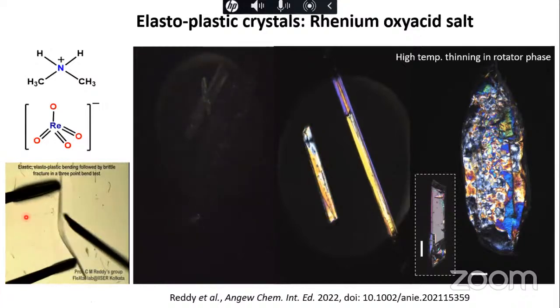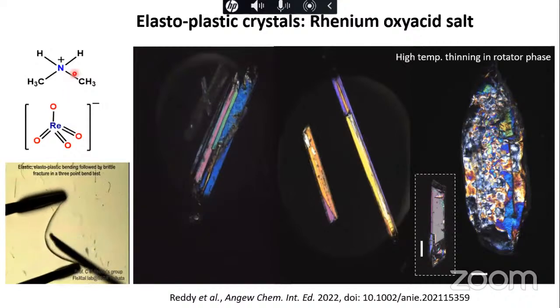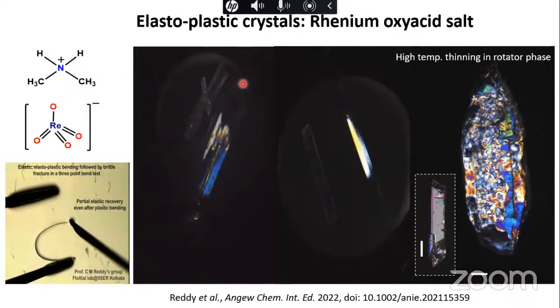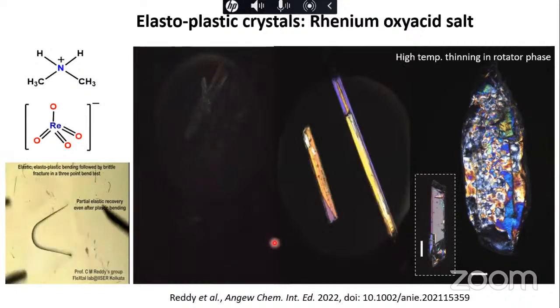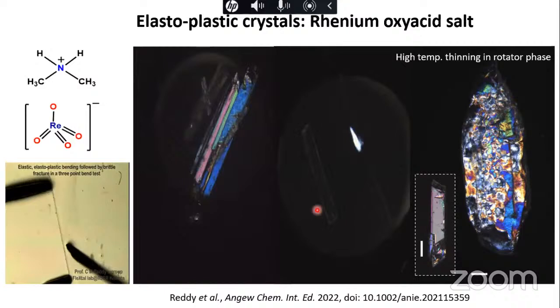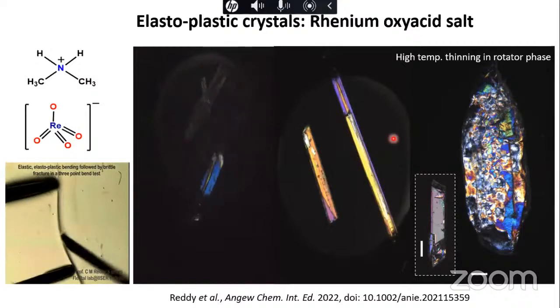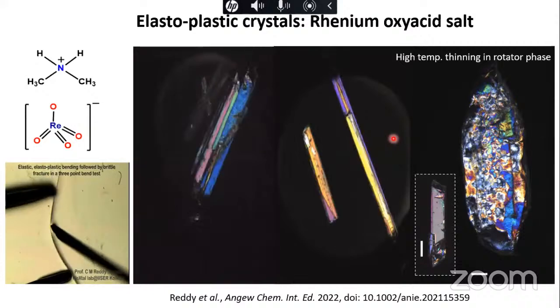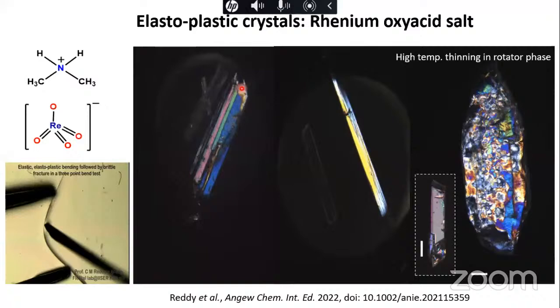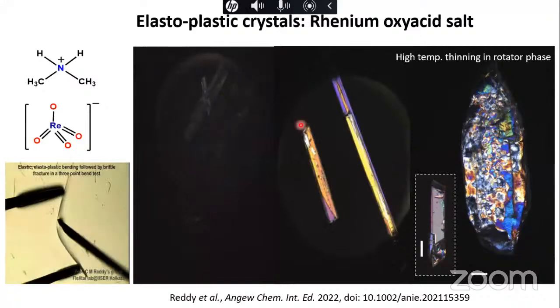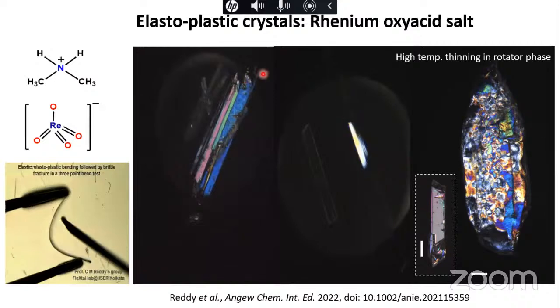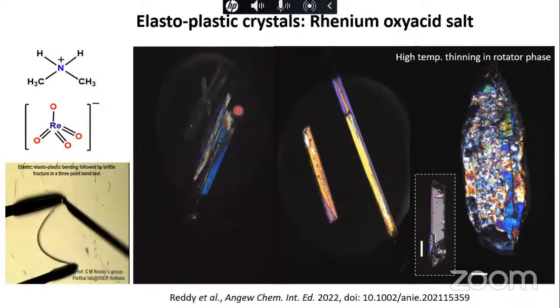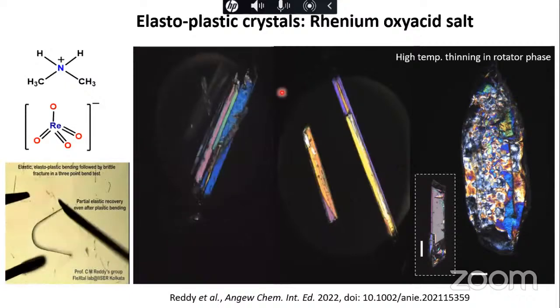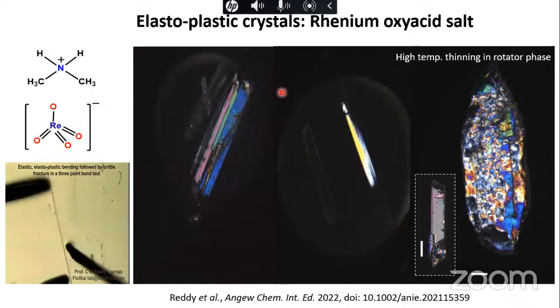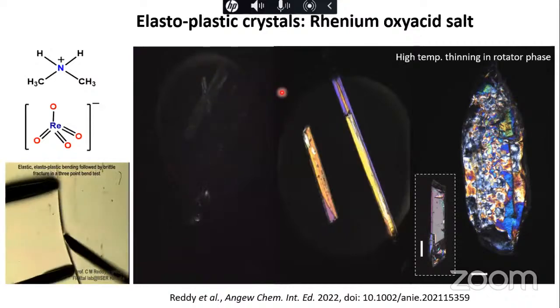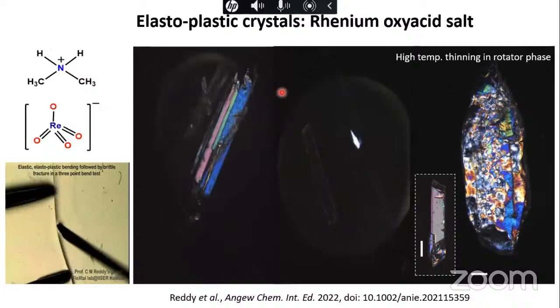At room temperature, these are like normal static crystals. But when you heat them beyond a certain temperature, as you can see, the crystals go into the plastically disordered phase. That means the molecules start rotating after a point, and it goes into the rotator or plastic crystalline phase. Once it does, it loses this iridescence. As you can see here, the phase transformation starts from one side and goes to the other side. Once molecules start rotating, the crystals also become more isotropic because molecules are not oriented in any particular direction. Because of that, you lose the iridescence in this type of crystals.